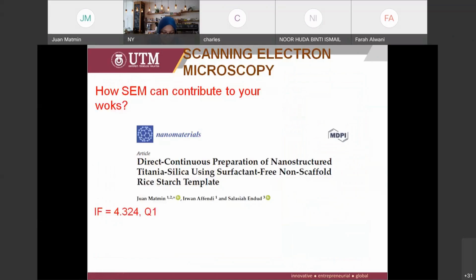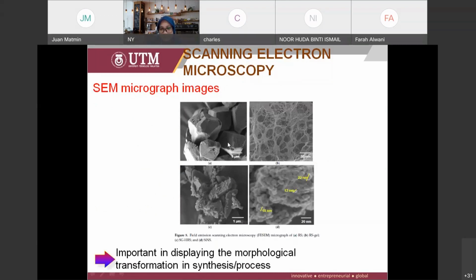So how can SEM contribute to your work? This is interesting. Okay, as mentioned in the first example on how I used DLS, supported with TEM and SEM, we are able to get a good image of a layered material. In this case, we propose a new preparation method, which we find is a direct continuous preparation method using a rice starch templated method. Okay, in this study, we use SEM micrograph images to display a transformation process.